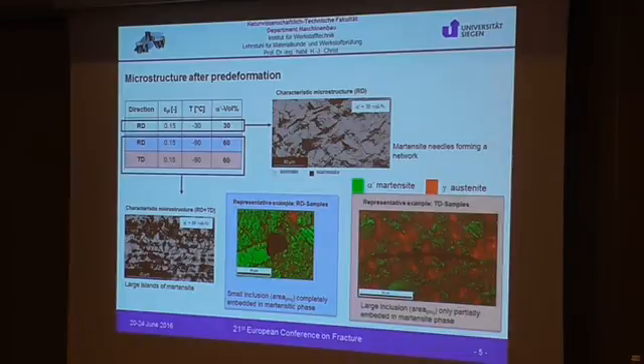The three predeformation conditions that I investigated are with 30% martensite, 60% martensite in the rolling direction, and 60% martensite in the transversal direction. We can observe already at 30% martensite that the martensitic needles start to form a network, a coherent network, whereas at 60% martensite, we can find large clusters of martensite in the microstructure.